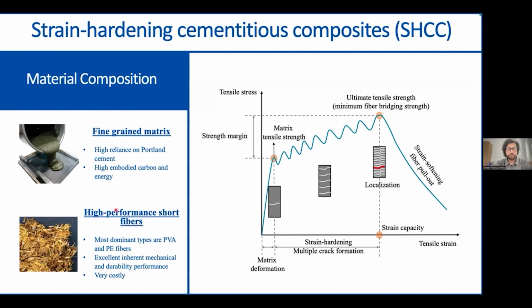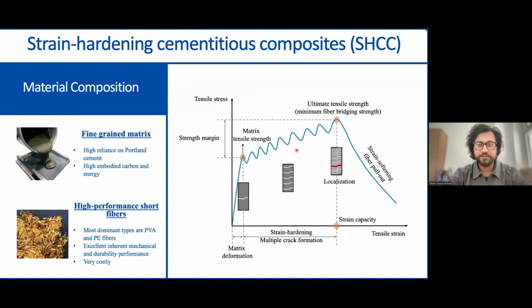And when we bring these two components together, it transforms the concrete from a brittle material into a pseudoductile one. So again, as you see here on the right-hand side, once the matrix, which is brittle, cracks at this point, the fiber starts to bridge the crack and transfers the load across the crack flanks. In this way, the composite develops many fine cracks and continues to carry the increasing load whilst still allowing large inelastic deformations. This is what gives SHCC its excellent tensile ductility, as you can see here, the strain capacities on the x-axis. And it also makes SHCC absorb a lot of energy during tensile loading, which you can imagine as the area under this curve.